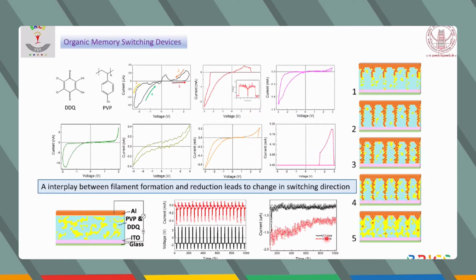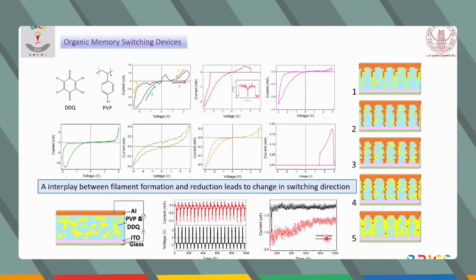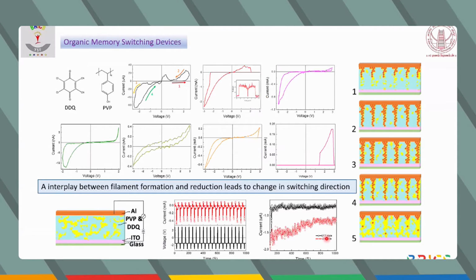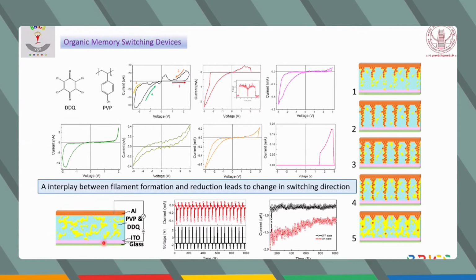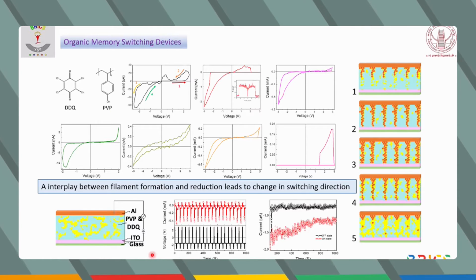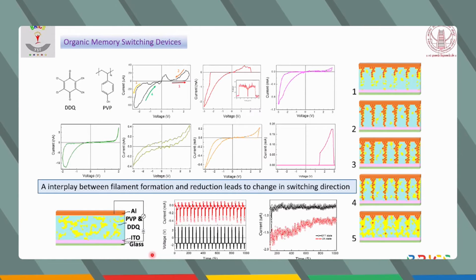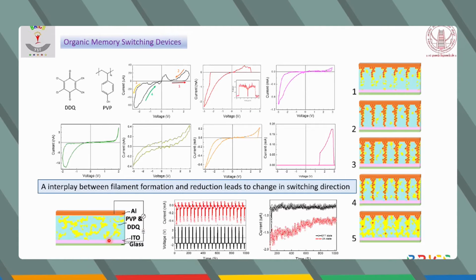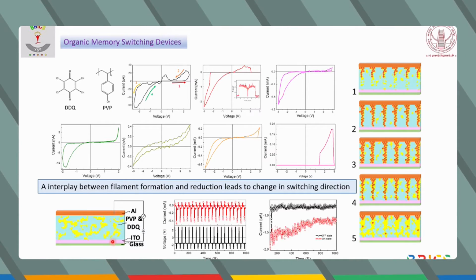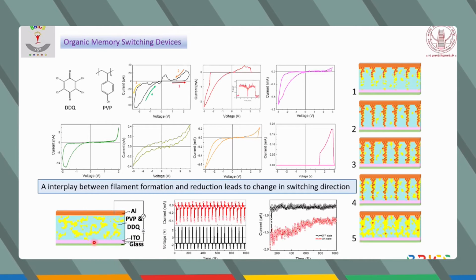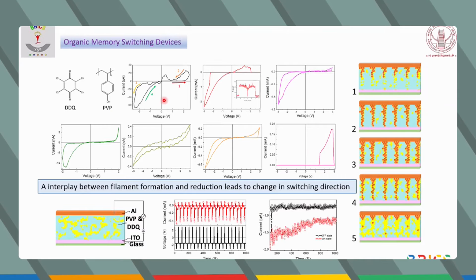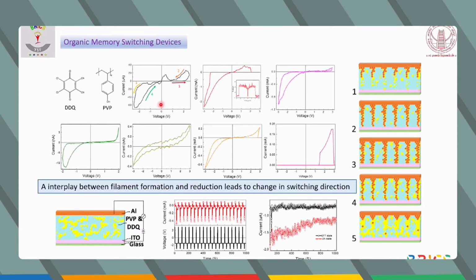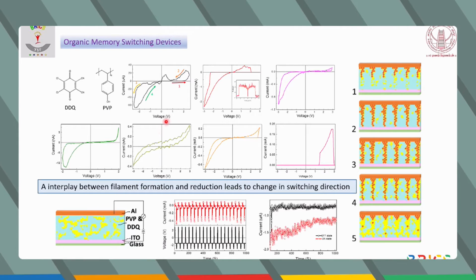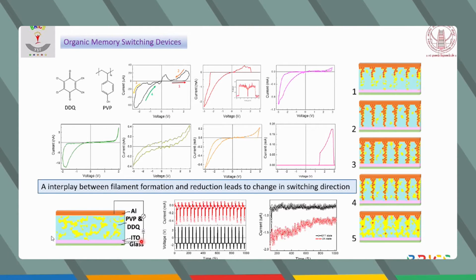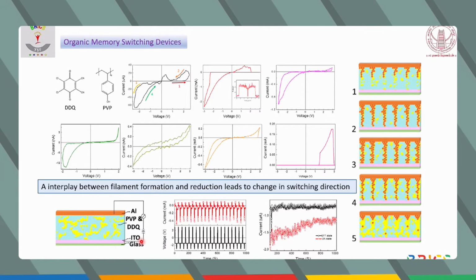Now next, once we studied the molecule closely, we tried to study the molecule by preparing bulk devices, this type of devices. So to prepare the bulk devices, we glue the film of this material in combination with another polymer called PVP. So it basically provides you a polymer matrix, right? And when we studied the IV characteristic of this device, we found that there is this switching behavior from these devices. And we saw that when we are varying the concentration of the molecule to that matrix, polymer matrix PVP, the switching direction is changing.